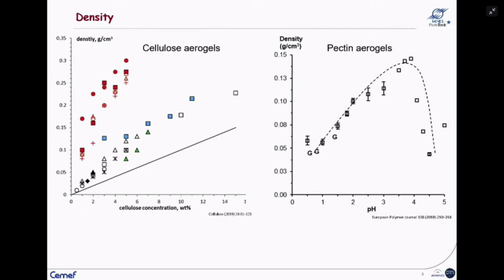What is interesting also, as I mentioned, is that the properties of the starting polysaccharide have to be well understood. And here is the example of the density of pectin aerogels as a function of the pH of the initial solution. And you see the density is very low, all data below 0.15 gram per cubic centimeter, but it varies a lot. 3 times you can vary the density depending if the starting solution is gelling or not. This is marked with G, with gels.